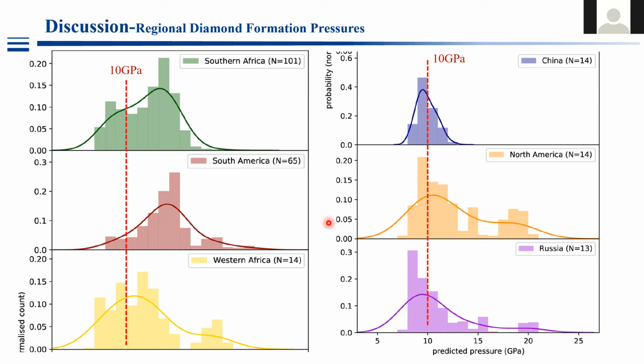In the end, it is a very sodic, sodium and potassium rich pyroxene equilibrated with the carbonated peridotite. Therefore, carbonates become very sodium potassium rich, and sodium and potassium carbonates have an extremely low melting temperature. That's why the sodium and potassium rich carbonated peridotite has a very low melting temperature at extremely high pressure.